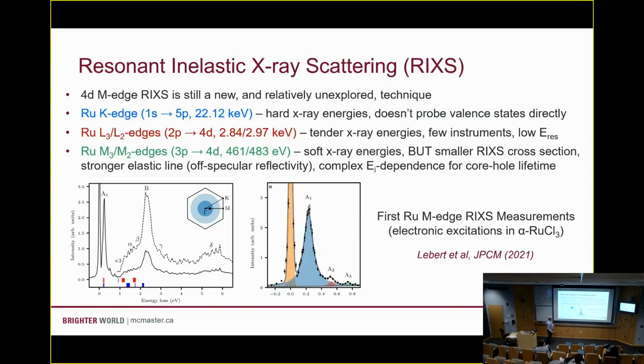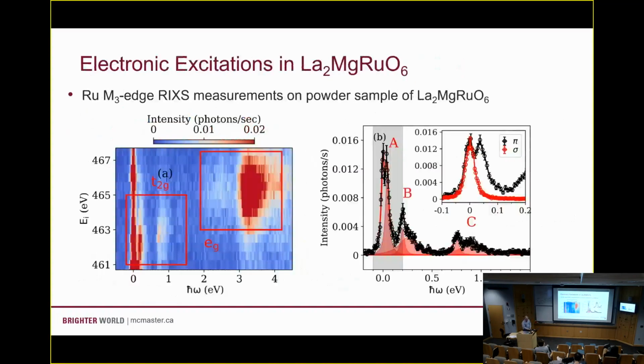And actually, the first measurements at the M edge that we recorded were for ruthenium chloride about 5 years ago by Ken and my old group at Toronto. Okay, so let's see what we can pull out from this first set of RIXS scans here. So I should say that in order to get this high stats scan here takes us about 10 hours. The count times here, if you can see, this is photons per second, and so you're less than, in many cases, 100th of a count per second. So not a fast experiment to do.